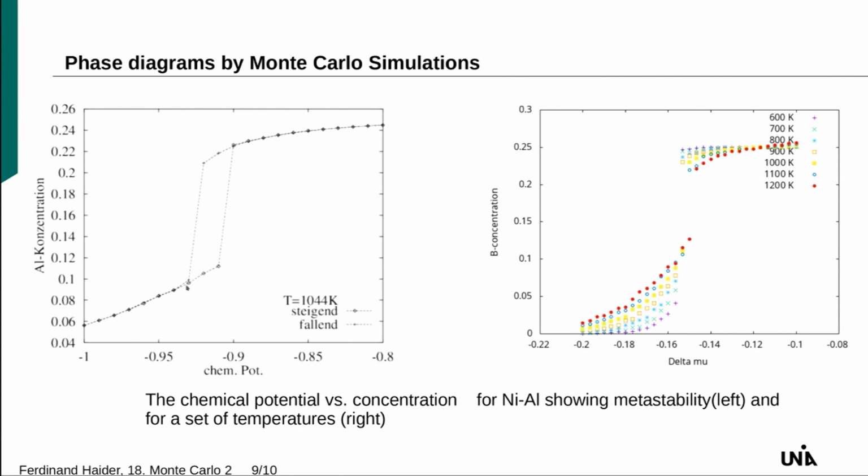And as I said, you have this strong hysteresis. This nickel-3 aluminum phase is an ordered phase, so it takes some time to nucleate. So probably, especially this branch of the hysteresis is a bit too far to the right, while disordering is typically much easier than ordering.